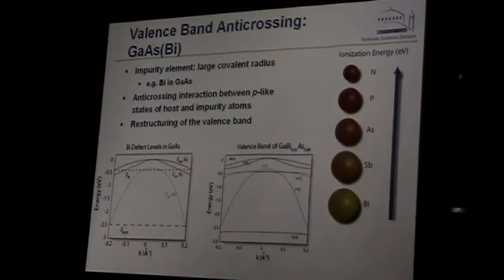So what's happening when you put bismuth into gallium arsenide? Bismuth is very large and very metallic, and arsenic is kind of middle of the road between nitrogen and bismuth. In this case, the electronic structure of the valence band is affected quite drastically because bismuth again produces a level inside the valence band. So it starts to anti-cross.